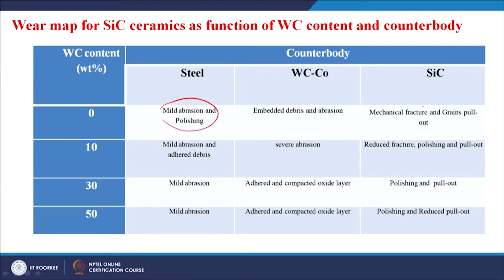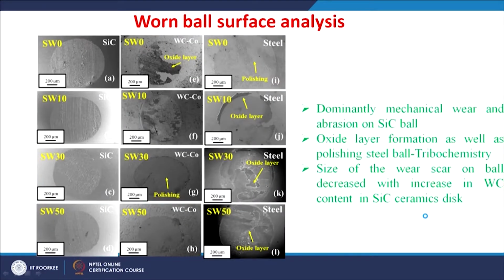Against silicon carbide, again there is only grain pull out and fracture, only change in the fracture is observed with increase in the tungsten carbide. So, with an increase in the tungsten carbide content, the fracture is reduced and it becomes more polished and reduced pull out. To understand the actual mechanisms, we need to also study the counter body